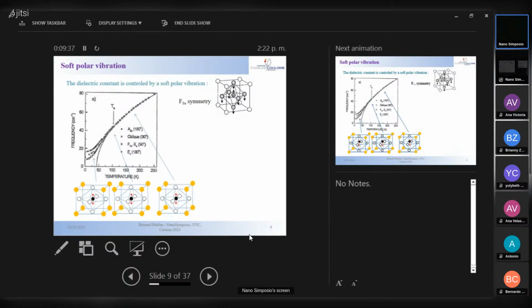And so, this mode here, you can measure it. For example, here, it has been measured. This is by Hyper-Raman, but I will go to that after. As a function of temperature, you measure the frequency of this motion, and you've got something which is decreasing very fast with temperature, and which goes to very, very low frequency. This is just to schematize this. Okay, it's simpler not to make the oxygen atom moving. So at high temperature, the atoms are moving fast, the frequency is high, and when you lower the temperature, the atoms are moving slowly, and this is what we call a soft mode.